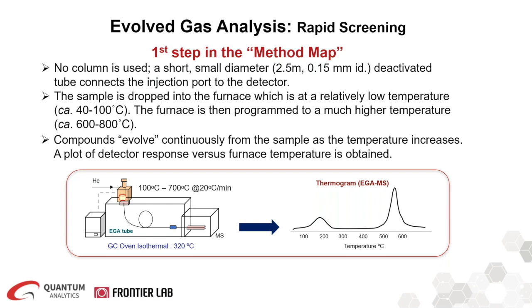To perform EGA, a short and deactivated tube is used to connect the GC injection port to the MS. The sample is dropped into the furnace, which is at a relatively low temperature. The furnace is then programmed to a much higher temperature. Compounds evolve continuously from the sample as the temperature increases. And then a plot of detector response versus furnace temperature is obtained, as you can see in this figure on the right-hand side. So the x-axis is the furnace temperature as well as the retention time, and the y-axis is the intensity.